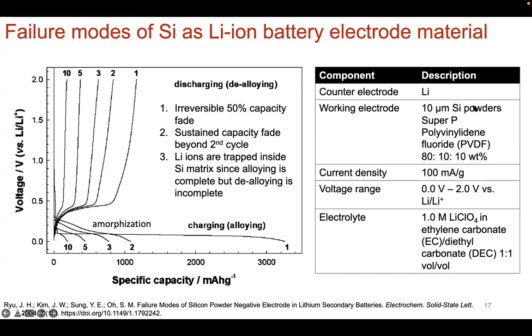But here in this particular example, there's 10 micron silicon powder, some conductive carbon, some binder in a weight percent distribution that is pretty within the realm of conventional composite fabrication. And what you see is there's dramatic capacity fade for these larger size, larger relative to what is state of the art, which is nano. So with larger size silicon powders, there's irreversible capacity, as you can see. So you lose a lot of this capacity that you don't regain. So here's the lithiation, here's delithiation. So you lose quite a bit of capacity. So there's greater than 50% capacity fade.